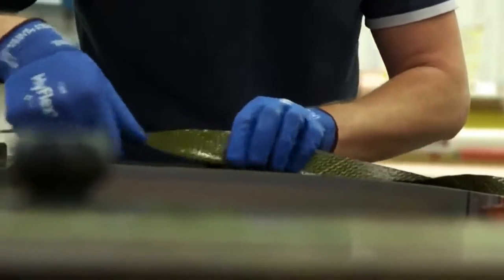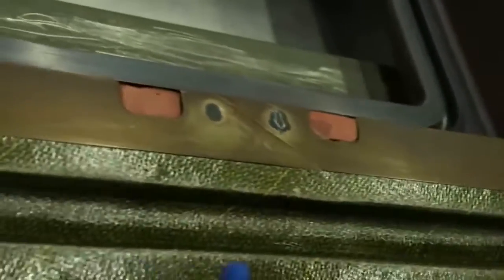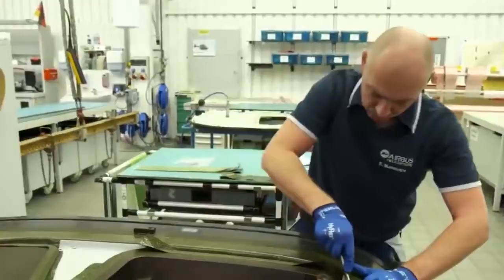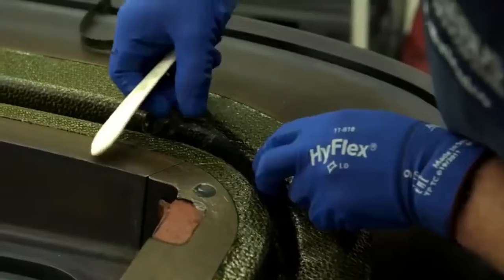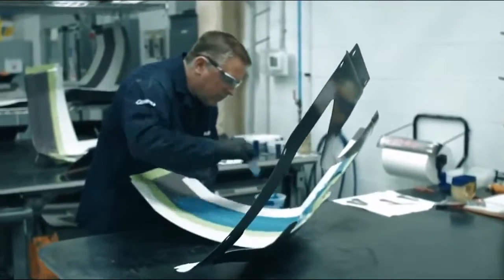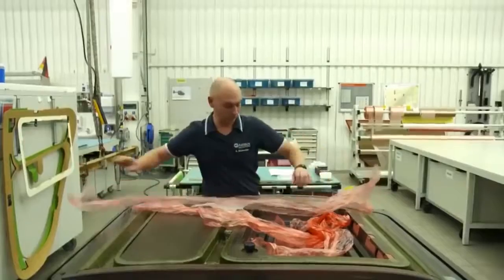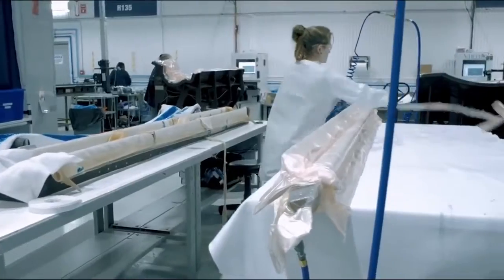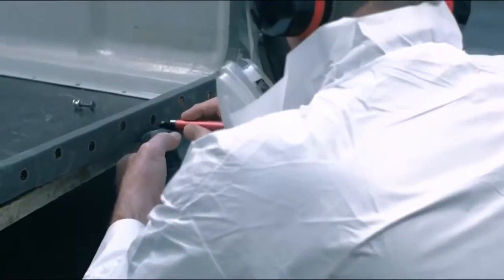First, sticky fiber material is put into the steel mold, the negative of the side door. The first layer of glass fiber is followed by 8 layers of carbon fiber fabric. In order to create the extremely strong carbon composite, the pockets of air have to be removed from in between the various layers. Pockets of air would make the material porous and unstable.